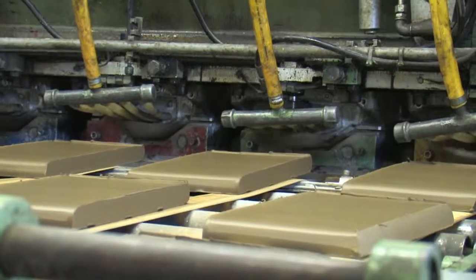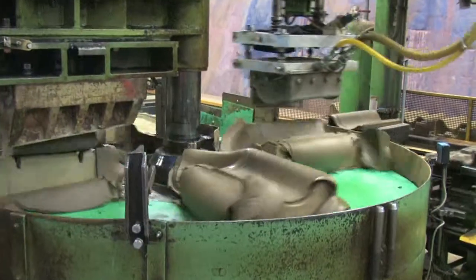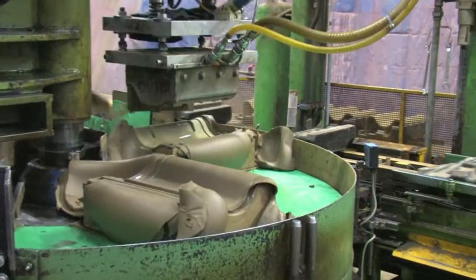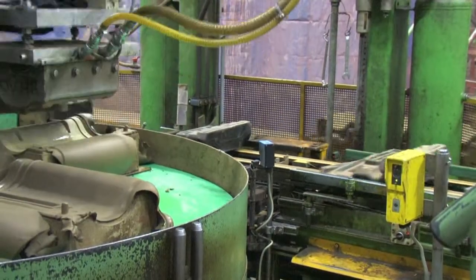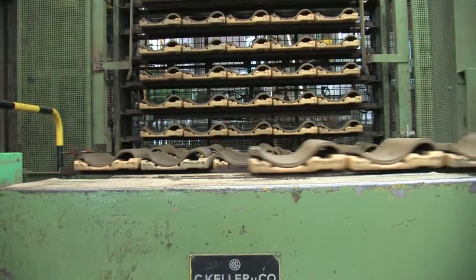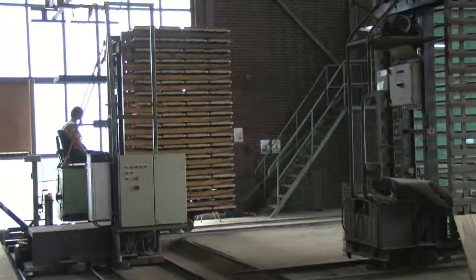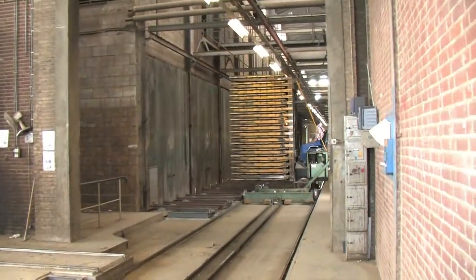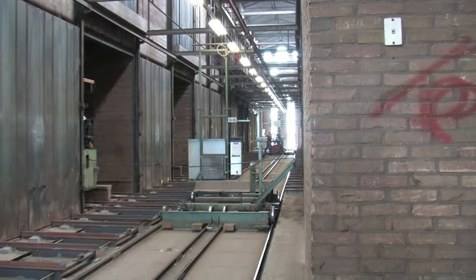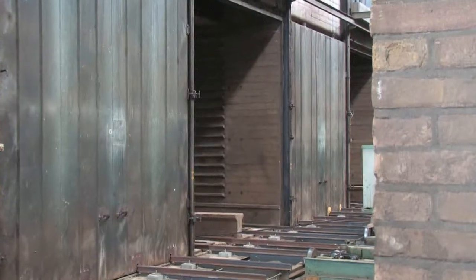The bats are pressed into tile shapes by special presses called molds. There are, of course, many different shapes and styles, and a mold is made for each different shape. The soft but molded tiles are now transported through the factory on conveyor belts and with the aid of forklift trucks to the drying area. The moisture in the tiles needs to be removed slowly to avoid cracking or distortion. The temperature in the drying rooms is monitored closely and can be gradually increased. The drying process can take several days.